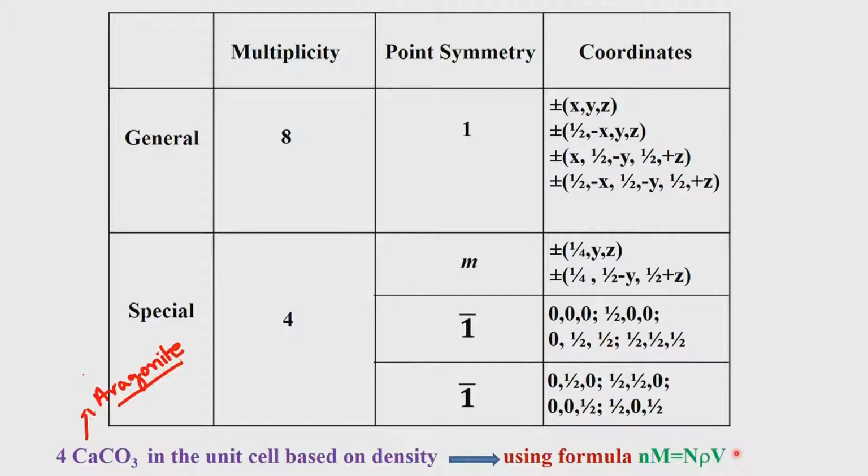We identify the space group, and this has been identified as Pmcn. Then we calculate the volume of the unit cell. So, we have the volume known in this expression. We know the volume, we know the Avogadro number, we know the molecular weight. The 2 unknowns are the number of molecules in the unit cell and the density associated with the crystal.